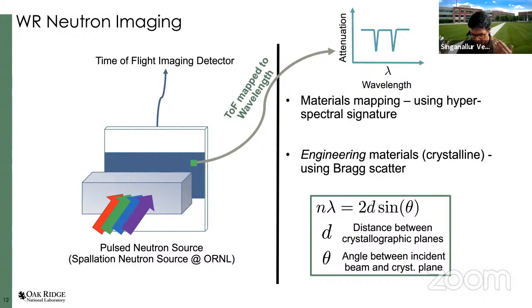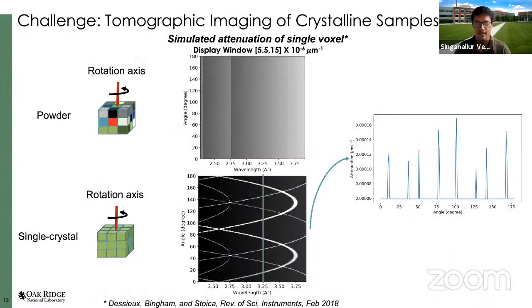So these are materials that can diffract using Bragg's law. That is, whenever the wavelength and the crystallographic spacing satisfy the condition lambda = 2d sin theta, you get a strong diffraction. And often this makes it hard to do CT with these materials. So while you can do imaging, when you start doing CT, there is something very challenging that occurs. So the summary is that when we have wavelength resolved neutron imaging and want to image crystalline materials, that is not easy to do. And here is a more precise reason for why that is true.